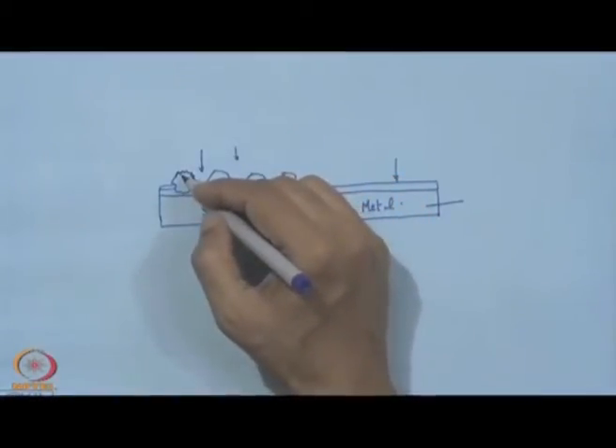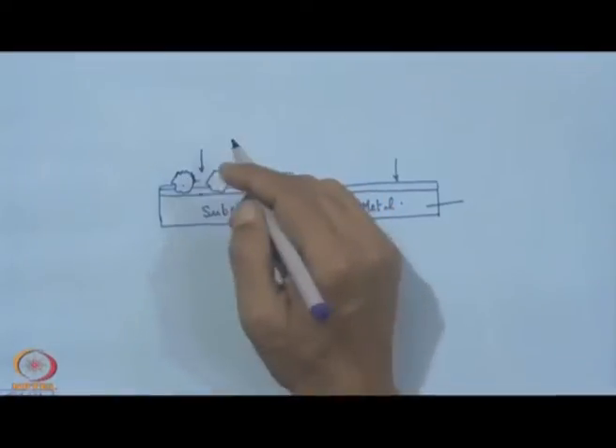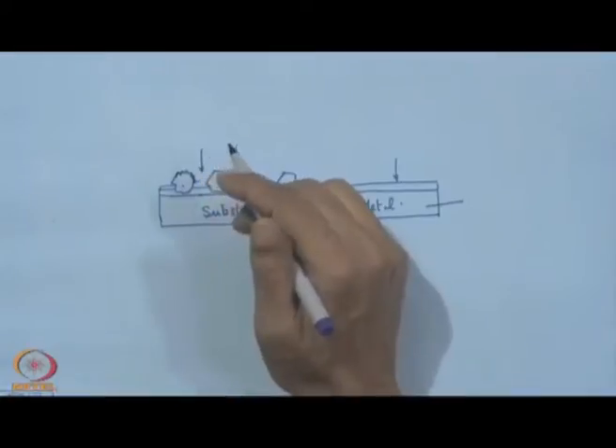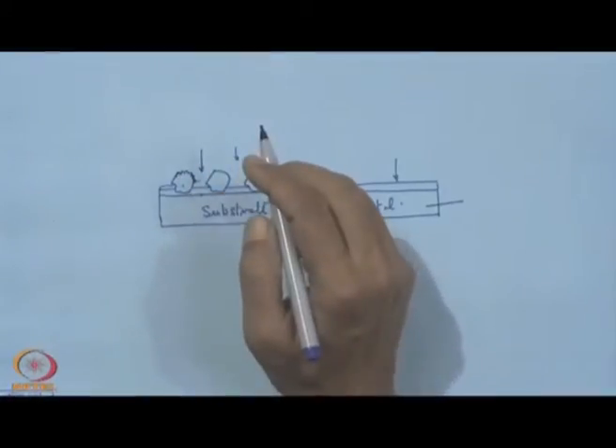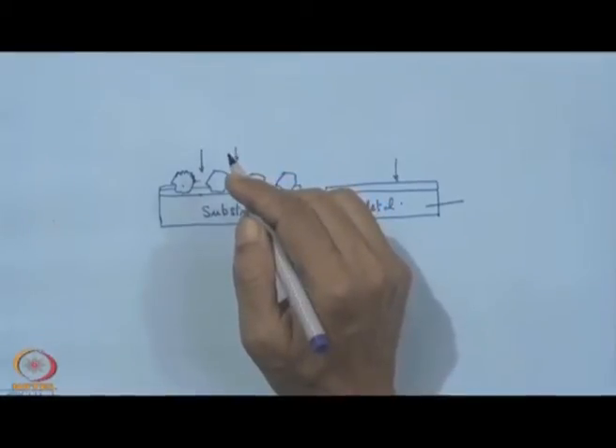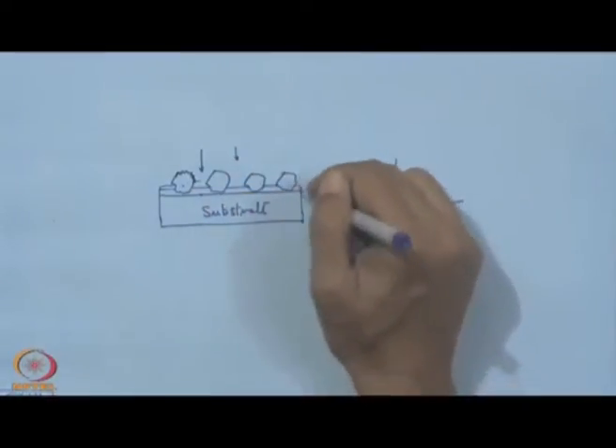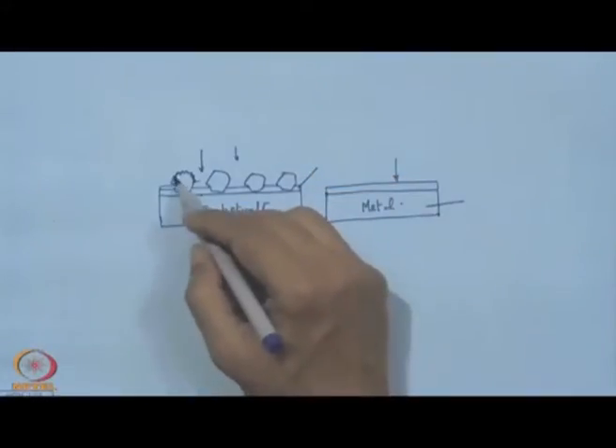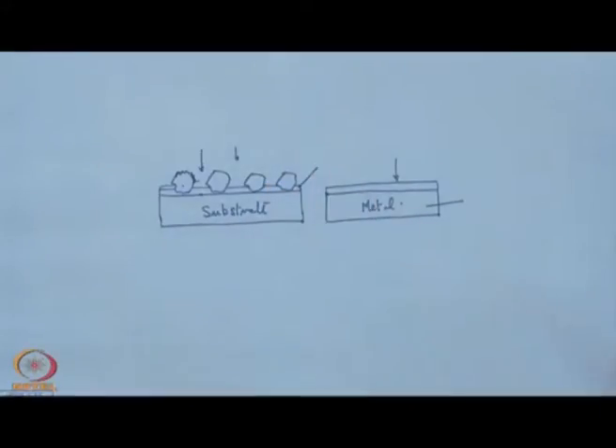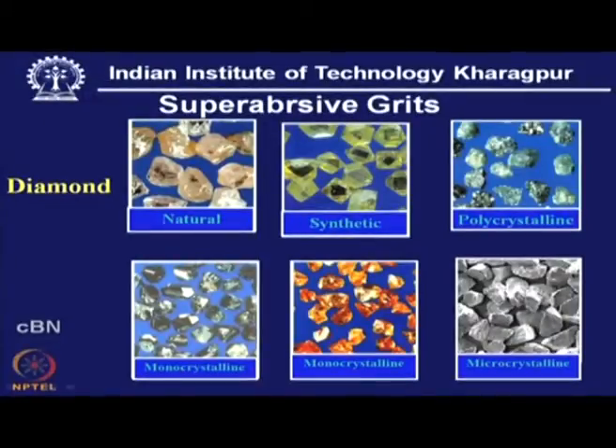So, one requirement is that there should not be any electrical conductivity, number 1, and number 2, if we can have a rough surface, that will always be to our advantage, enhancing the anchorage of the electro deposited metal on the surface of the abrasive. But at the same time, we also see this man made blocky single crystal. It is perfectly grown, it is used for very difficult tasks. When this difficult grinding task is assigned to this wheel, then we have to have such kind of crystal.